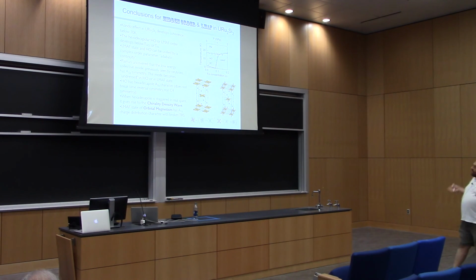Well, that's basically, okay, the last comment I have. Sean flashed, I can find the same transparency, where he is measuring on this very nice piece of the crystal the B1G phonon, and does not see any sensitivity, which is fantastic, no leakage of that mode in any other forbidden geometry, which should occur if C4 is broken. And that was done at 8 Kelvin. So, in fact, we have no evidence of broken C4 symmetry.